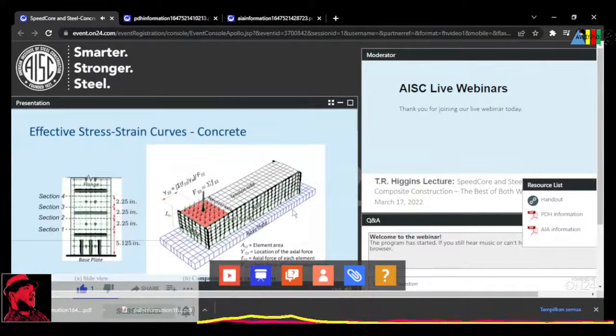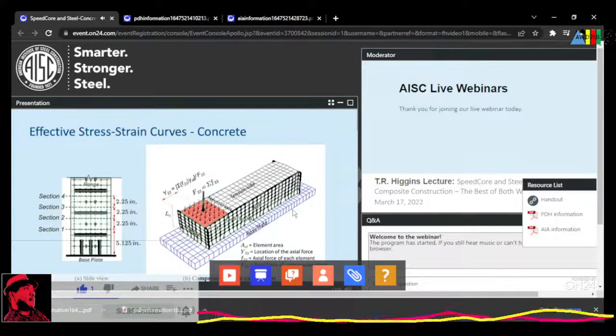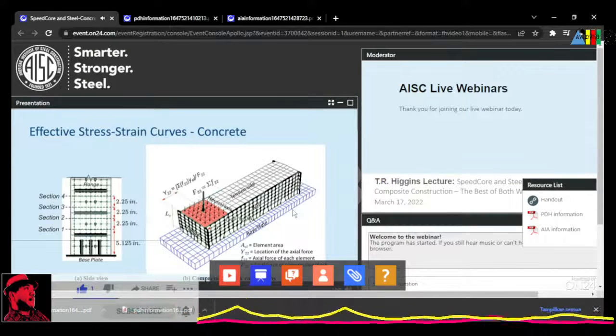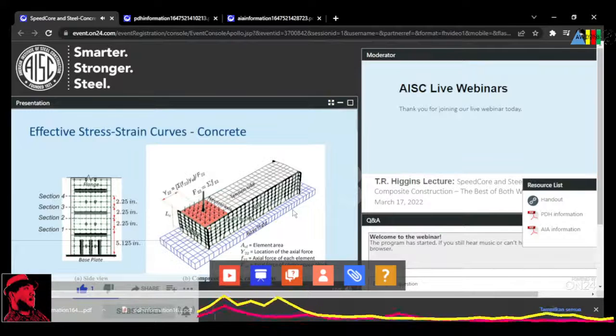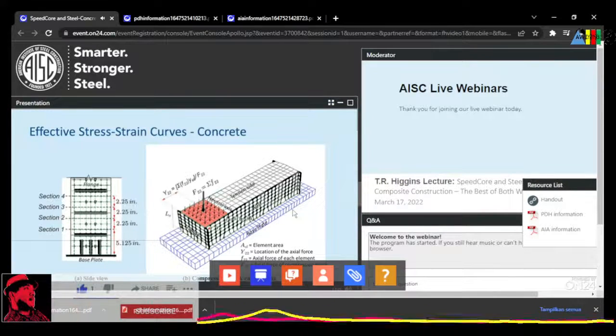Similarly, for the concrete infill, we were able to account for the effects of transverse interaction and confinement by post-processing results from the 3D monotonic finite element analysis. The effective stress strain curves for the concrete in compression, which was confined, were also derived.